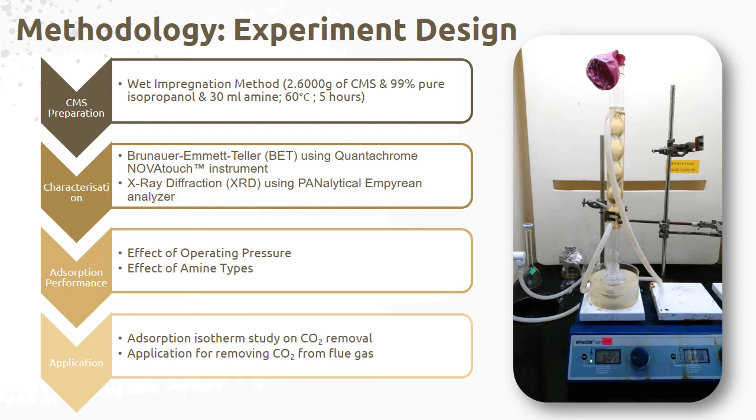The textural property were obtained from nitrogen adsorption-desorption isotherms recorded at Quantachrome Novatouch instrument. The surface area, pore volume, and pore size were measured by using the multi-point Brunauer-Emmett-Teller (BET) method. Apart from that, the crystalline structure changes of the samples were investigated by X-ray diffraction (XRD) using a PANalytical analyzer. In the next part of the experiment, the CO2 capture capacity were performed in a